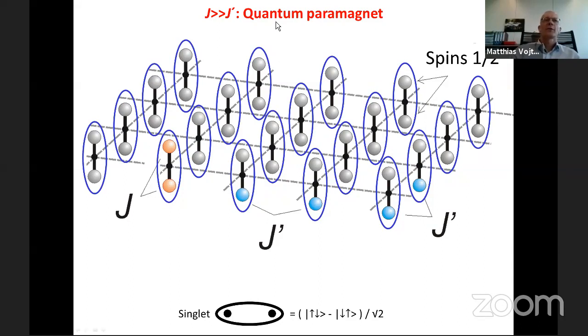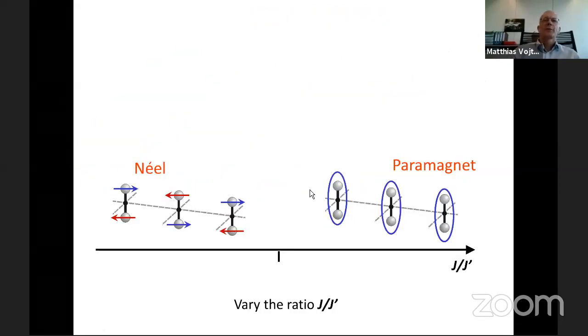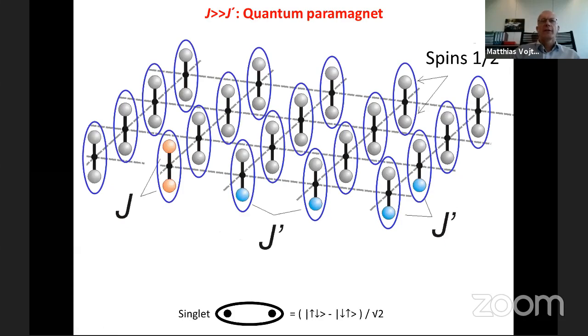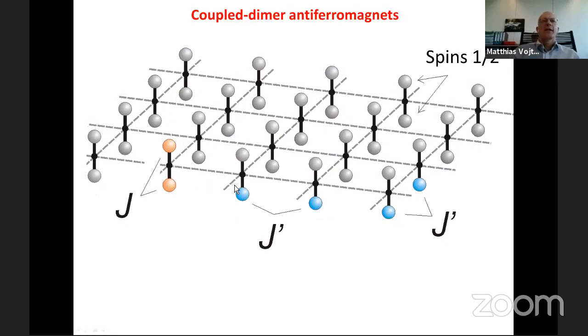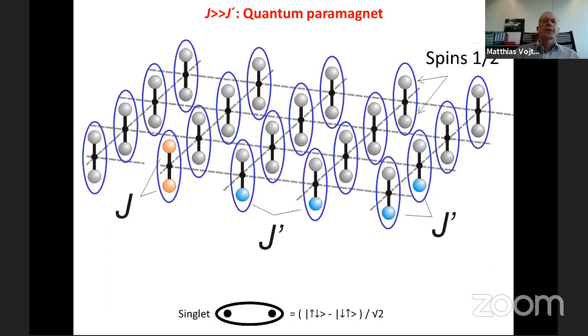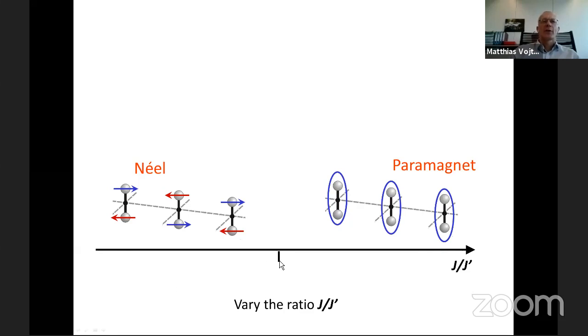This is already an interesting state. You would call it a quantum paramagnet, because this is a state where at zero temperature, the spins point nowhere. So all magnetic expectation values are zero. Now we can start from this state and vary the ratio J over J prime. If you instead make the coupling J prime large and J small, the opposite limit, we essentially have two weakly coupled square lattices, which is known to order antiferromagnetically. This immediately allows me to construct the zero temperature phase diagram of this system as a function of the ratio J over J prime. I go from this singlet quantum paramagnet to an antiferromagnetic Néel state with spin orientations as shown here.